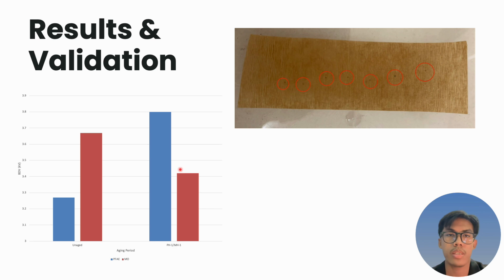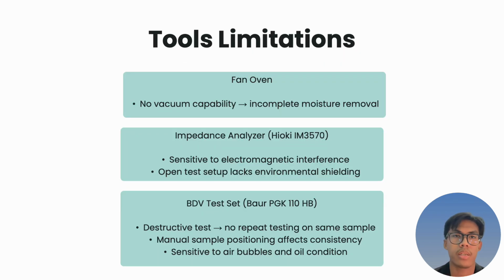So BDV results support this observation, with PH1 achieving 3.80 kV, while MH1 dropped to 3.42 kV, confirming that PFAE offers better thermal resilience. So this image shows the puncture hole after breakdown occurred. So these findings are validated against literature that reports ester oils offer higher fire points and environmental benefits but are more sensitive to moisture. So, tools limitation.